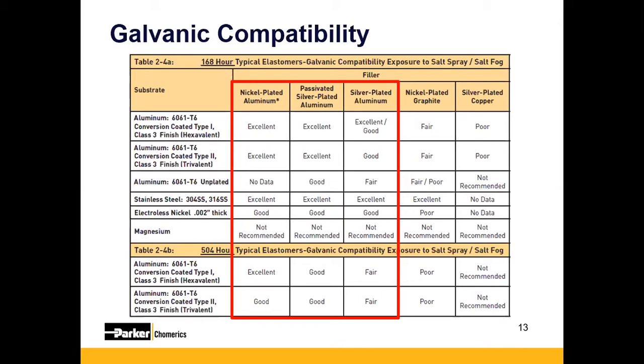When you move down the chart, as you saw in the previous chart, magnesium is a very active material. It's very difficult to gasket a magnesium housing. I know it's very attractive to a lot of engineers because of its low density, but it's just not recommended in conjunction with EMI gasketing. And really what we've done with this table is we've taken that galvanic series and done a lot of the testing at 168 and 504 hours salt fog exposure of our gaskets as well as the enclosure materials. So we've really put together a determination of what the best mating materials are in terms of minimizing that corrosion and increasing the life cycle of a lot of these applications.